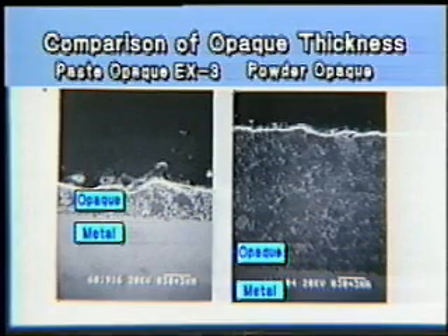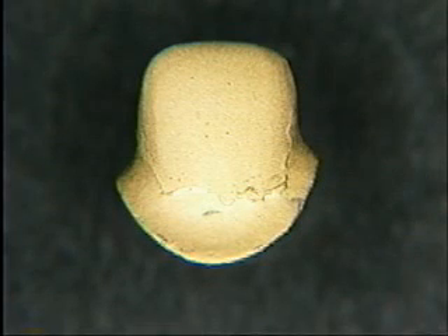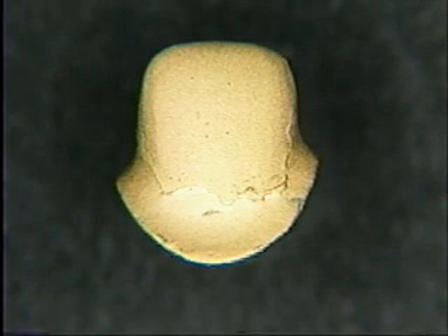This picture shows the comparison of paste opaque and powder opaque after baking. Paste opaque gains the same effect with about 1/3 the thickness of powder opaque. The thinner opaque layer leaves more space for enamel buildup and makes it easy to regain the color shade of ceramo metal crown. Up till now, gold paste is applied to prevent the black line, in other words, the phenomenon of a dark color shade at the margin.